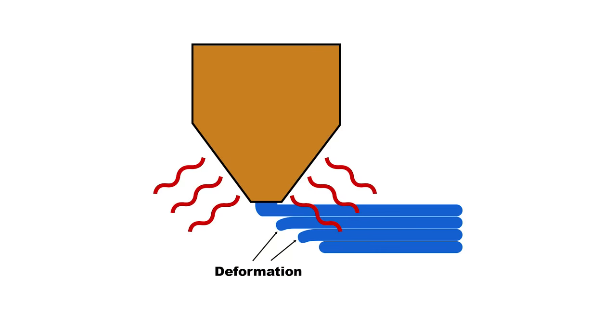Now, the first mistake I see a lot of people make when printing miniatures on a home printer is they look at the absolute minimum layer height their printer can print, and that's what they print at. That actually will work against you. You do not need super thin layer heights to print miniatures that look good. They can actually create more side artifacts and increase stringing. If you look at this image, the nozzle in all cases is going to give off radiant heat. There's nothing you can do about this. You have to print at a high enough temperature to reliably extrude the plastic. The problem is that if you're printing at too thin a layer height, that radiant heat can cause prior layers to reach their glass transition point again and soften and deform on you.